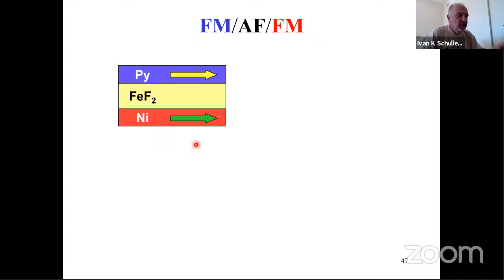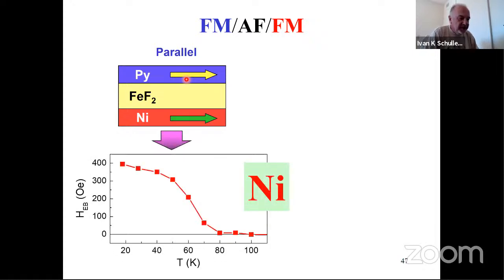It's a very simple experiment: ferromagnet, antiferromagnet, ferromagnet layer. Suppose I orient the magnetic moment of the bottom layer to the right, and the top layer to the right, and I measure the exchange bias of the nickel. I can do it with the magneto-optic Kerr effect. So I can measure the magnetization of this nickel layer as a function of temperature, and lo and behold, as I told you earlier, the nickel has an exchange bias: the loop is shifted to negative values. It starts at the Néel temperature of the antiferromagnet, at roughly 78 degrees or so, and it's very big.